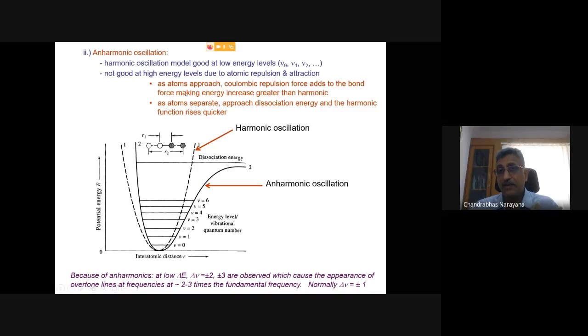There are two things which happen. Because of the Coulomb repulsion, this potential doesn't remain a parabola. It actually starts changing from the parabola. And also, when it becomes very, very high energy, the atom starts dissociating. And that's why you will have anharmonicity in this. And this is very important because the energy states, as you go higher, start crowding. And that is why you can also have transitions, which usually in harmonic approximation, we can have only plus or minus 1. Whereas in anharmonic systems, we can have plus minus 2, plus minus 3, which are called overtones. That means second harmonic and third harmonic are possible. This is possible only because of this anharmonicity.